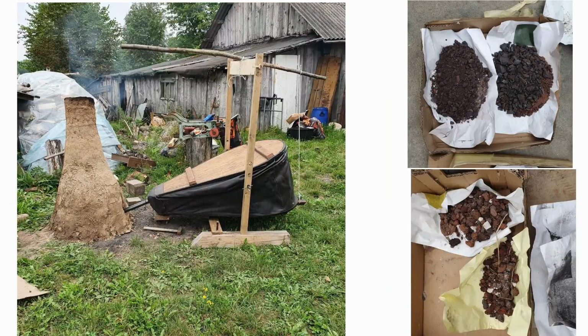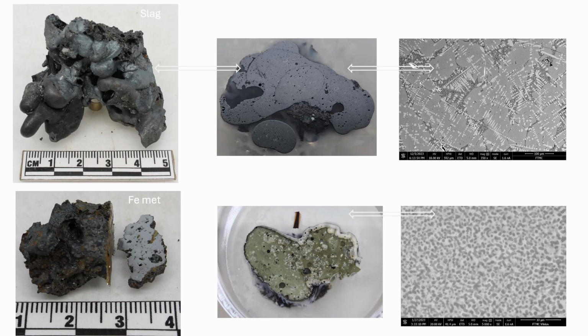During an additional trial, we crushed the ore into 1 to 2 centimeter pieces and mixed it with siderite ore at a 1-to-1 ratio. The resulting slag was not green and had the highest iron content, comparable to amounts found in archaeological slag. The elemental composition and microstructure of the slag were also similar to those of archaeological slags, containing fayalite and wüstite phases. And here you can see slag from this last experiment and can compare it to that from the previous tests.